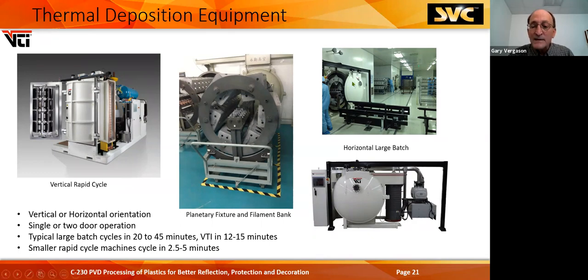And there are lots of horizontal machines out there. You pull the carrier out, you reload the filaments. A lot of times these filaments are on a separate little slide that comes out so you can get to them. But you can see these fixtures. These are four-sided fixtures. And each one of these holes for an e-nickel mask, you're looking at $300 to $400 a hole. So these fixturing packages can get very expensive very fast.